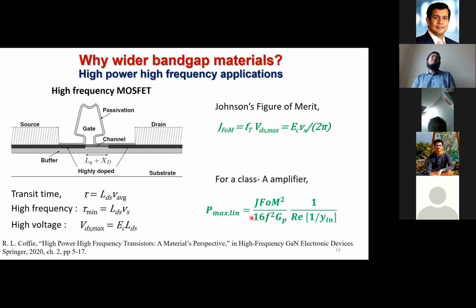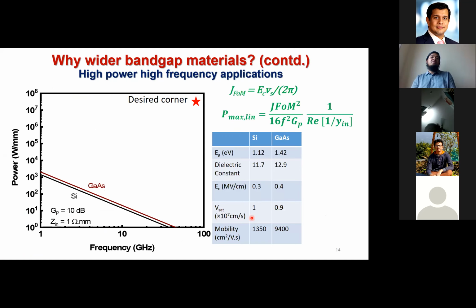Now again, if you look at our material options, the common materials for high frequency application are silicon and gallium arsenide. Gallium arsenide is popular for high frequency because it has a much higher mobility than silicon. In this plot, on the x-axis, we have the frequency in gigahertz, and on the y-axis, we have the linear output power of a class A power amplifier in watts per millimeter. The desired corner is on the top right, where we have the highest power at higher frequency. Silicon and gallium arsenide are in the same range because they have a similar band gap and similar critical electric field.